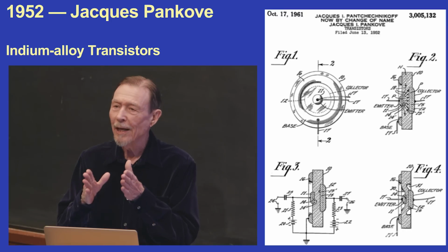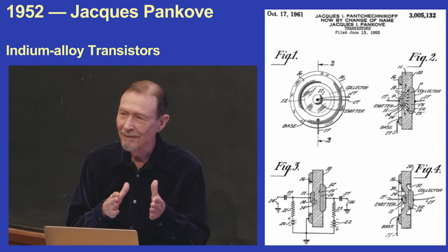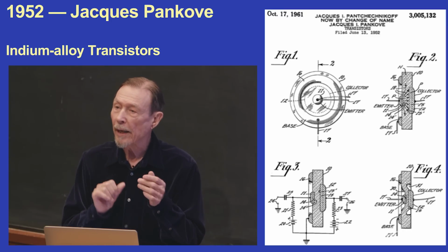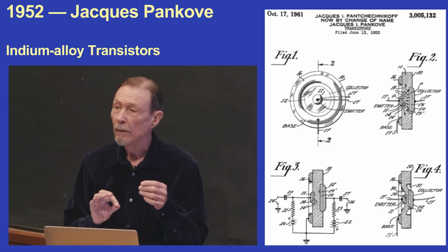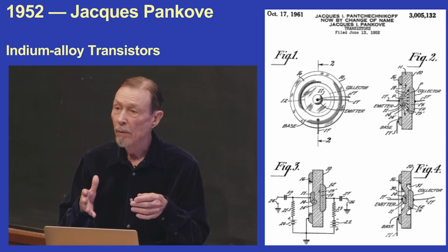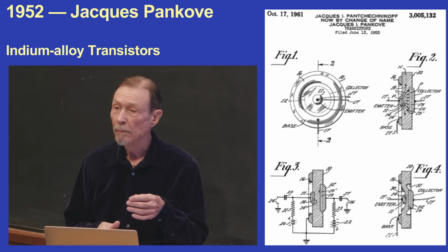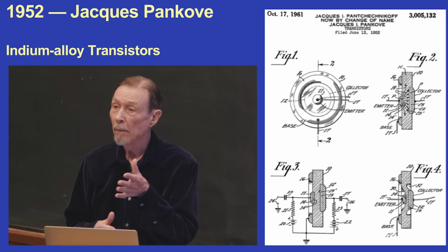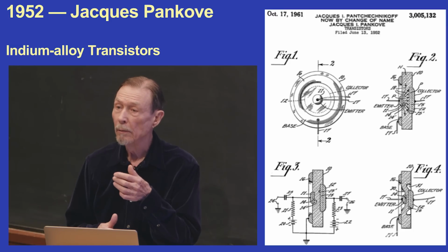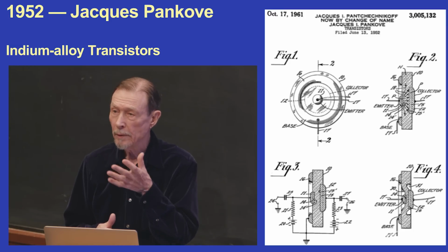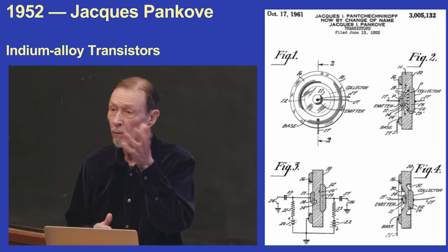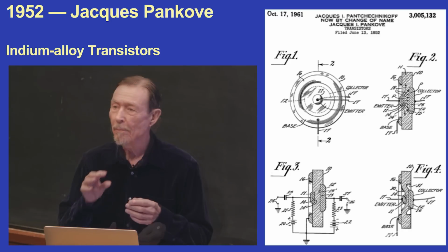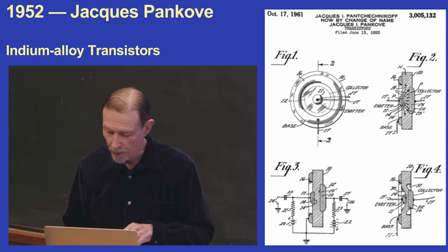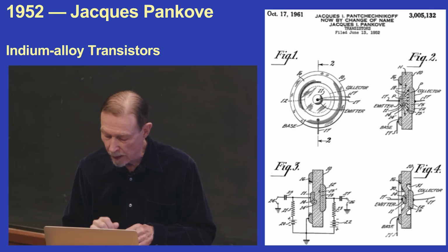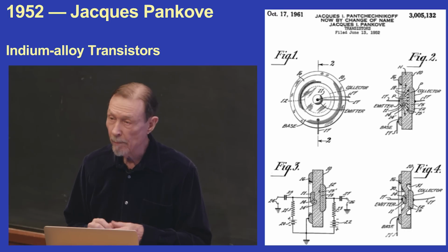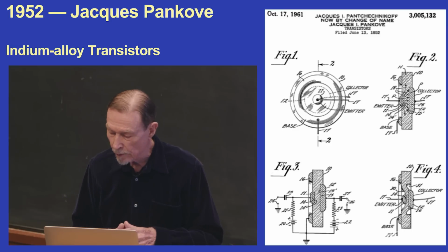And the germanium that had dissolved in the indium crystallized back out on the germanium that was there. Well, the germanium that was there was N-type, and indium is a P-type dopant. It takes an electron away, and what's left is a hole in the valence band. This was a PNP transistor, P from the indium on the left, P from the indium on the right, and N-type because that's what you started with.